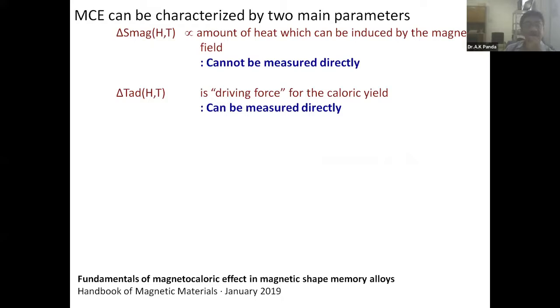Now, what I told you, delta S mag and delta T adiabatic, these are the two important parameters to gauge your magnetocaloric material, but nevertheless there are problems. Delta S max is the magnetic entropy change, the amount of heat which can be induced by the magnetic field. But there is a problem: it cannot be measured directly. That is, delta S mag cannot be measured directly. And delta T adiabatic is a driving force for the caloric yield. You can measure it directly, definitely.